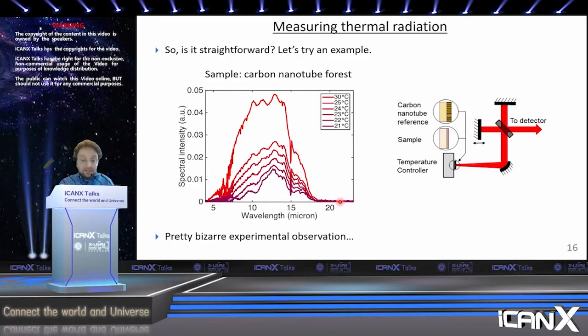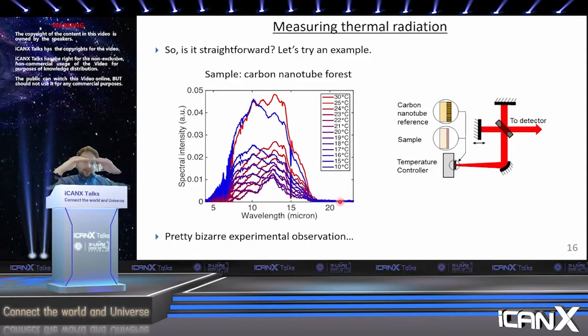But if you keep going, something really strange happens. Here's the data at 20 degrees, 19 degrees, 18 degrees, 17 degrees, 16 degrees, going all the way down to 10 degrees Celsius. And all of a sudden your spectral intensity starts going back up instead of continuing to go down. This is really bizarre, and it is just counterintuitive. It really goes against some fundamental laws of thermodynamics. And that's a big, big problem, right?